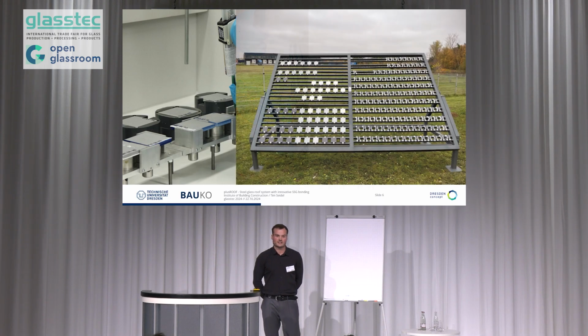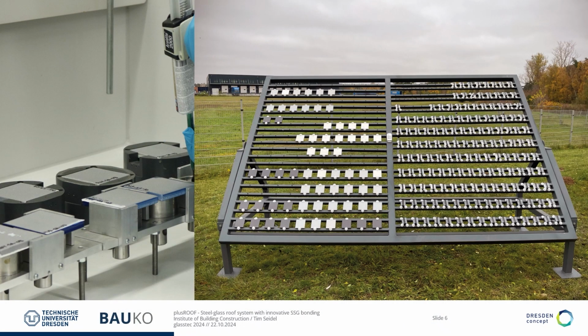First, we investigated whether the adhesive bonds well to common anti-corrosion coatings. To do this, we tested various coatings and application methods in small part tests. Material aging was also an important point, as can be seen here in an outdoor weathering stand.